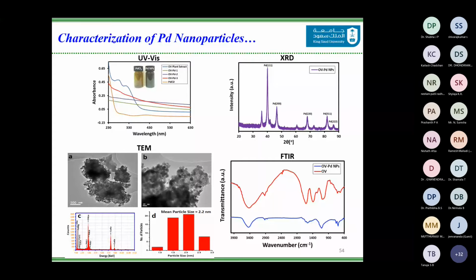As you can see, the UV is indicative of the formation of palladium nanoparticles, whereas the XRD is revealing the crystalline nature of the palladium nanoparticles, along with other diffraction patterns. However, this could be due to the phytomolecules or some crystalline substance present in the phytomolecules. The particle size is amazing here. We got an average particle size of 2.2 nanometers using this plant extract.